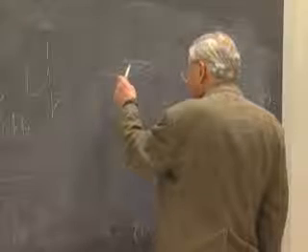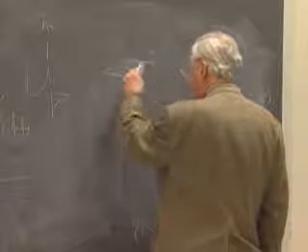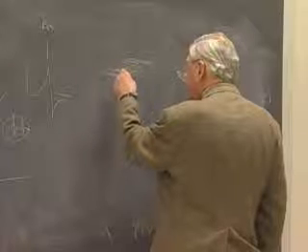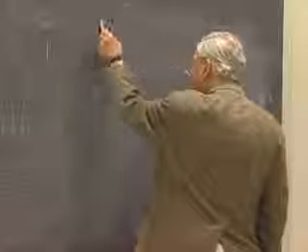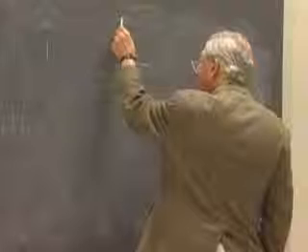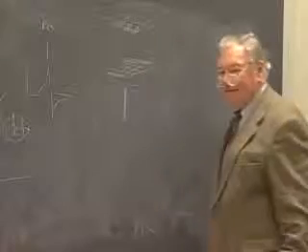Now, if this crystal is transparent and you shine a light through it, these little regions bounded by lines of 0 displacement act like little lenses. So if you pass a beam of light through it, you get a bunch of bright maxima, little focused spots on the sheet.